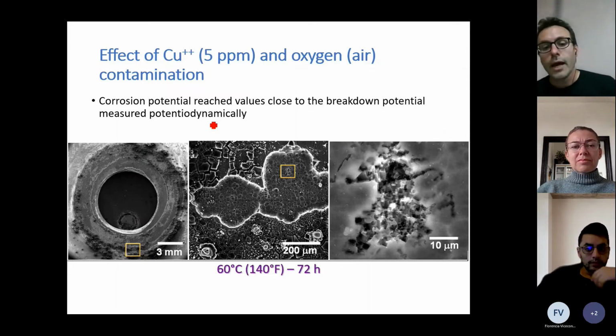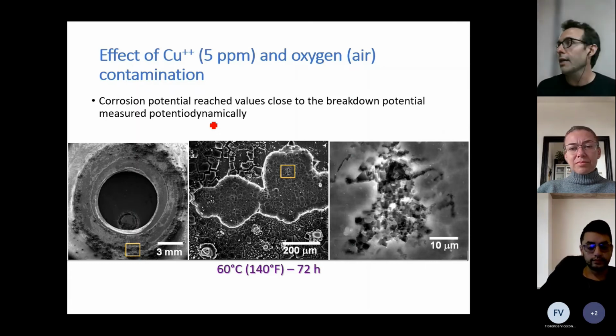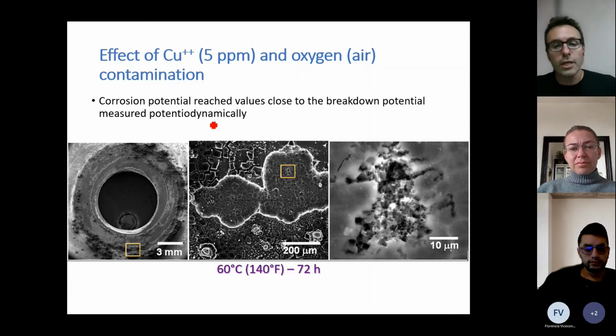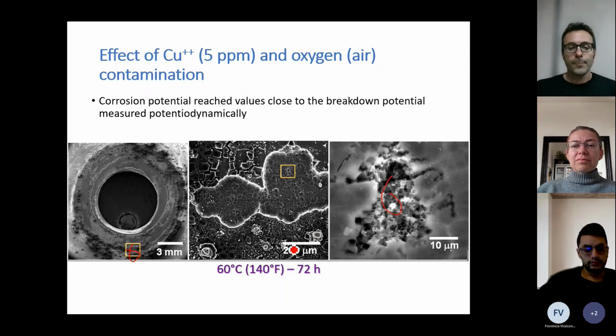And if you take your sample and watch it in the scanning electron microscope, what you see is what we show here. So we have attack underneath the crevice, and we see crystallographic peaks here. And this was done after 72 hours at 60 Celsius. So the takeaway point from this slide: don't let copper ions get in contact with aluminum. Aluminum doesn't like copper ions.